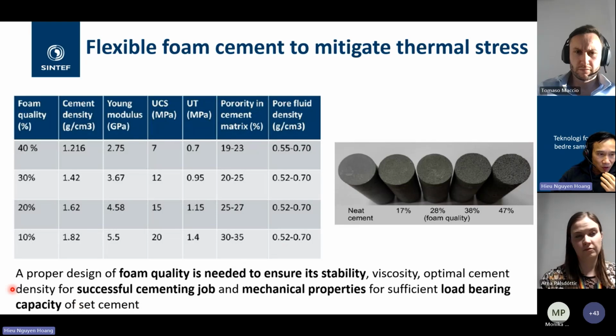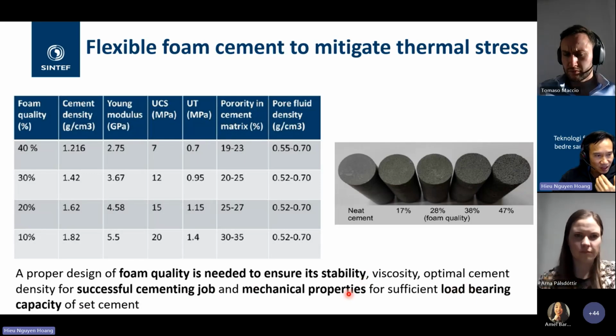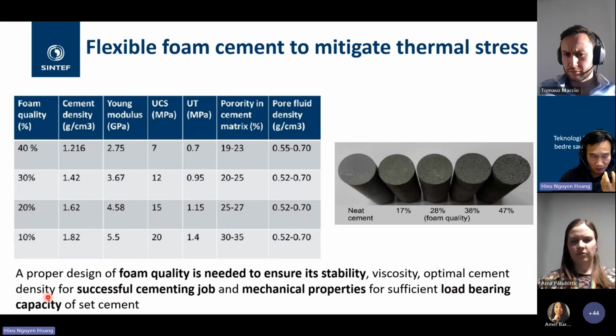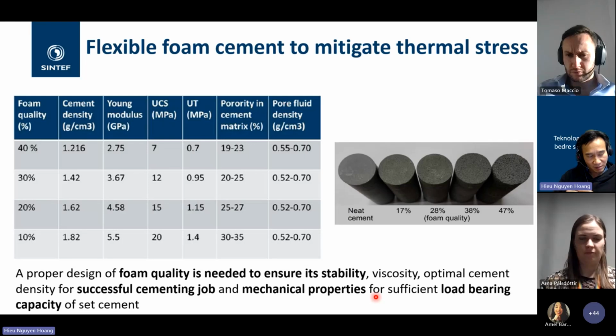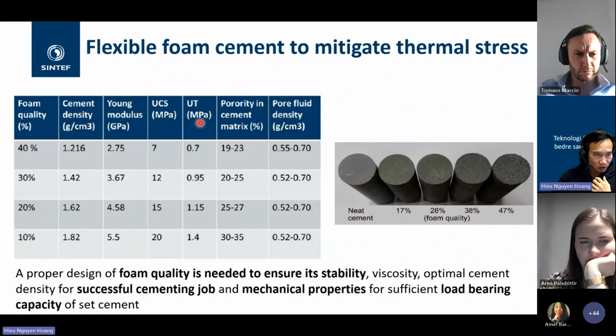And here you see the proper design of foam quality is very crucial to ensure stability and optimal cement density, cement lightweight for a successful cement job, and also to ensure the mechanical properties of foam cement for sufficient load-bearing capacity when the cement is hardened and set. In this table, you can see the influence of different foam quality on the cement density, and also mechanical properties like Young's modulus, compressive strength and tensile strength of cement.